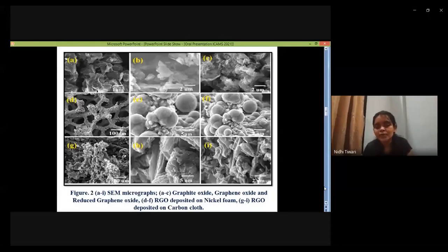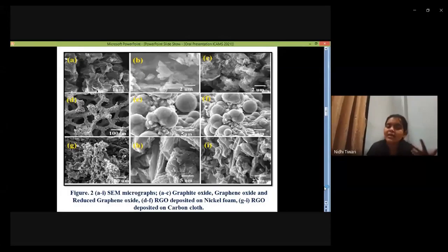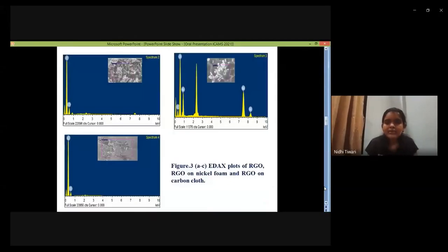There you can see a spherical microsphere kind of morphology, which I can say increases the surface area, and so it increases the electrochemical, supercapacitive behavior. For carbon cloth, we can see a crumpled sheet-like morphology. Then these are the EDAX patterns, which show the presence of carbon and oxygen, but on nickel foam, some amount of nickel is also seen. Then these are the mapping patterns.